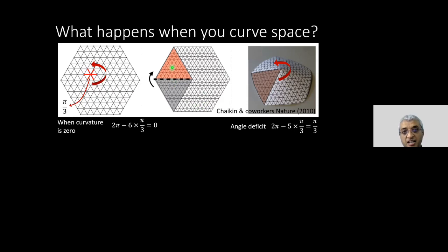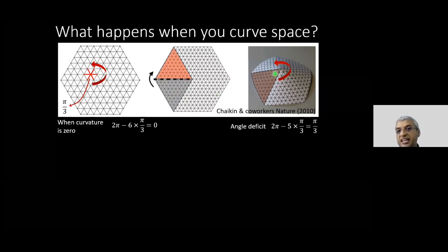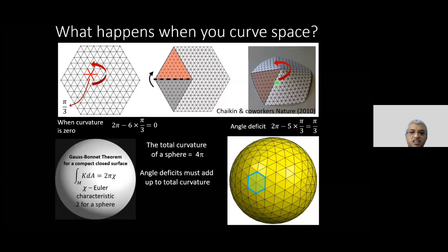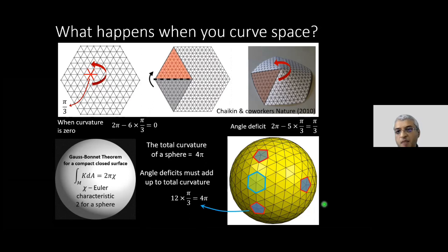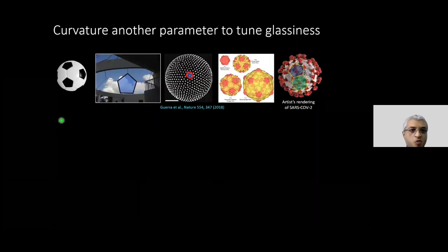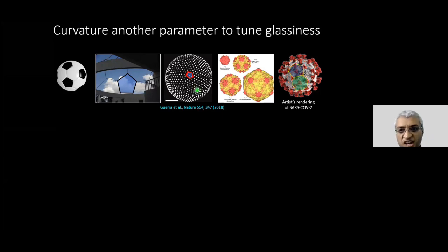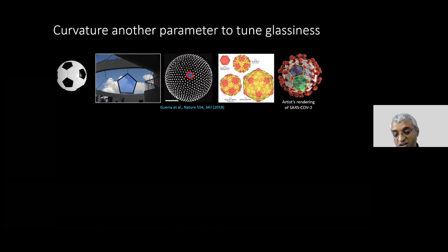Okay, but the minute I do the following, I take a cut, and now I overlap the orange and the gray regions. Now you're going to have basically this sort of a shape, and for this sort of a shape, if I were to go around in a circle, I'm going to now have a missing triangle, so I'm going to pick up an angle deficit, which means whenever there is a curvature on a surface, I'm going to pick up an angle deficit. Okay. Now for a sphere, we know that the total curvature is 4 pi, which means the angle deficits have to add up to 4 pi, which means I have to have 12 pentagonal defects. Okay, and this is precisely why a soccer ball will have 12 pentagons. Colloids, colloidal crystals on a curved surface will have 12 pentagons. Your SARS-CoV-2, at least the artist's rendering of it, has 12 pentagons. Okay.